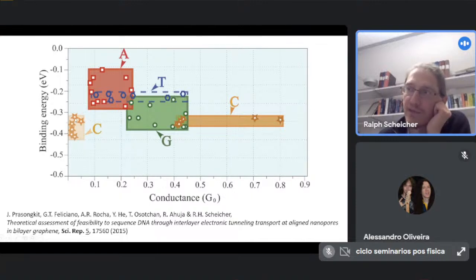And so we have very low coupling here and basically get almost 0 conductance enhancement. And then thymine, which is kind of overlapping with both adenine and guanine. So in practice, if this is a realistic prediction, the conclusion would be that this bilayer graphene setup would be quite well suited to distinguish between A and G, but would be difficult to distinguish T. T could look as an A or a G signal.